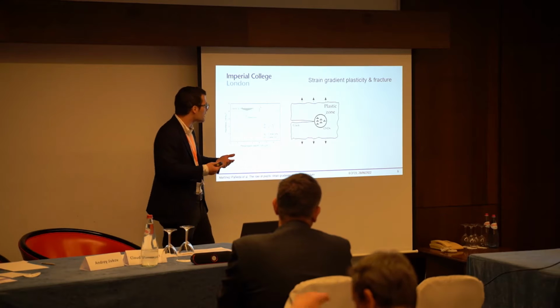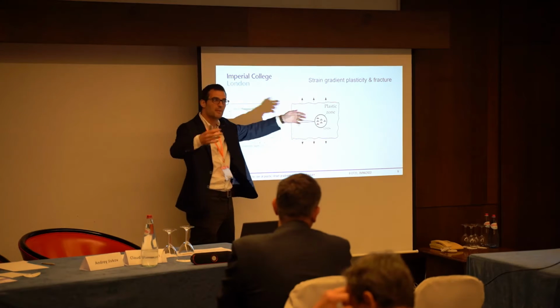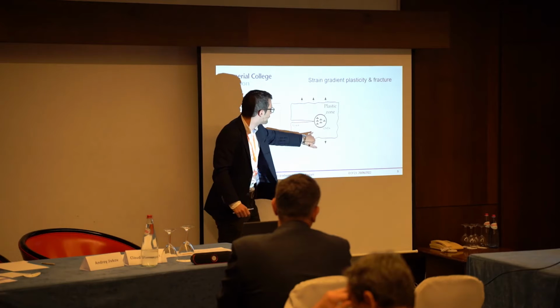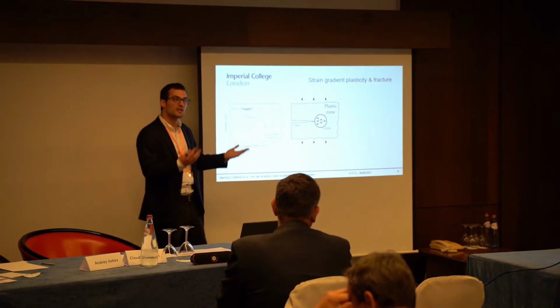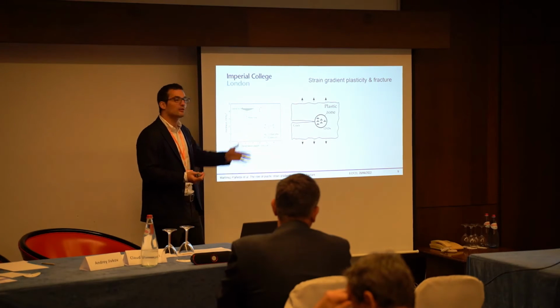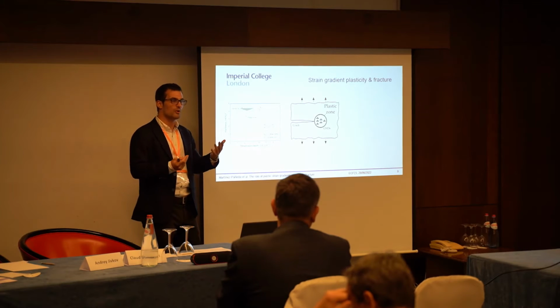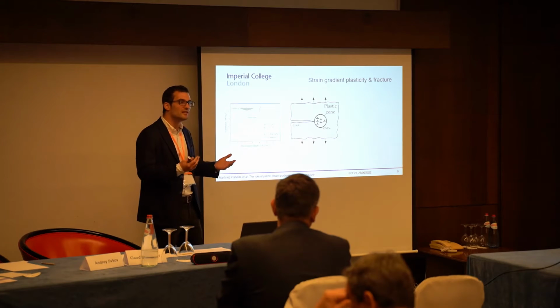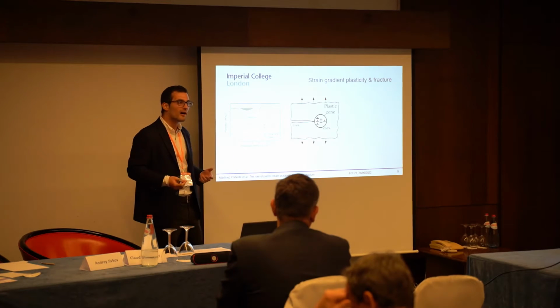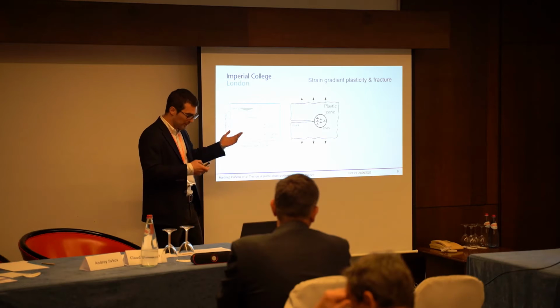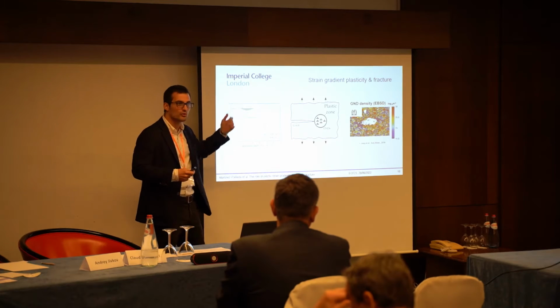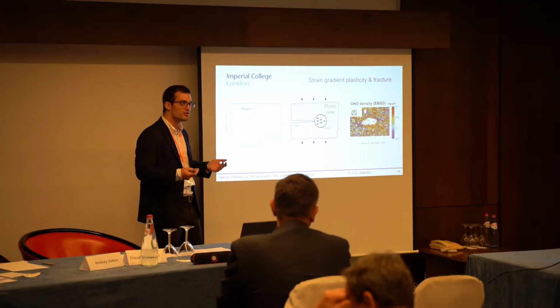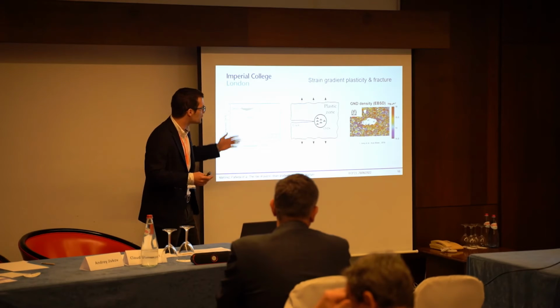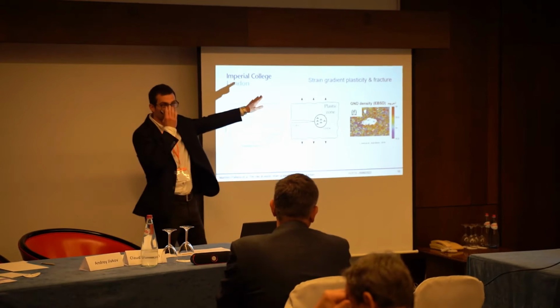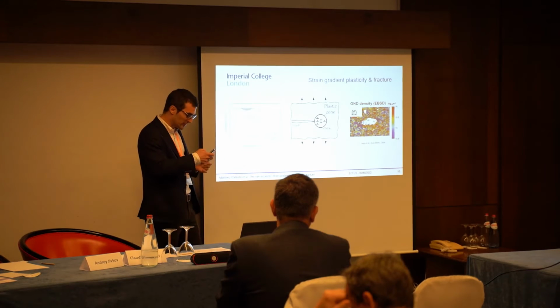You would expect that in cracks, most often, not always, sometimes you have plastic collapse and there's a lot of plasticity, most often you will have a plastic zone that is physically small, near your crack tip, and that contains very strong spatial gradients of deformation. So you would expect to see quite a lot of GNDs and plastic strain gradients playing a role there. You would expect to see these local hardening mechanisms that arise due to the plastic gradients. In fact, nowadays you can use high resolution EBSD and you can measure GNDs ahead of cracks and inclusions, and you see plenty of GNDs ahead of cracks and inclusions. So those things are happening in there.